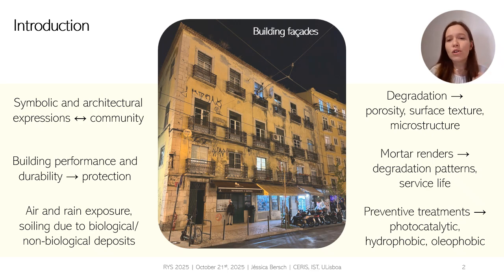However, the facades are constantly exposed to air and rain. They are also prone to soiling due to biological and non-biological deposits. If the materials of these facades suffer degradation, their properties may change, such as porosity, surface texture, and microstructure. When we have mortar renders as coating for these facades, these renders influence degradation patterns and service life. And that is why it's so important to think about preventive treatments.